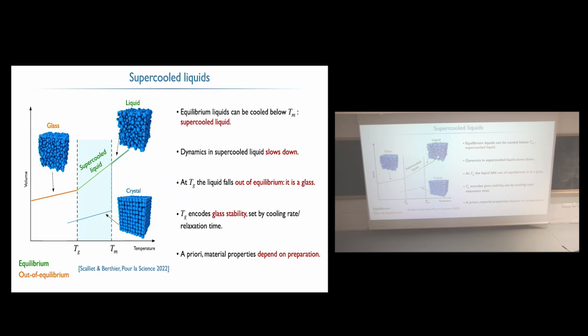It's disordered here. You can see that there's no arrangement. The point of cooling rapidly is that you want to avoid getting trapped in the crystal. So remember that this is a first order phase transition, so it actually takes some time to nucleate the crystal and for it to actually invade the system and transform into that. So in experiments, when you cool rapidly, you actually avoid the formation of this.